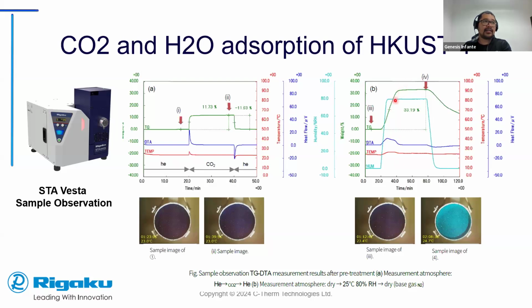And then, as the humidity is being stabilized, it saturates the MOF. But then you can see here, this is really what you want to see, is how does the MOF behave once you want to release that water, right? In a passive way where you don't introduce any energy to the system, you can see that the rate of water loss is a lot slower than the water intake in this case. And then you can see here that at some point when water is actually coordinating within the MOF system, there's a color change from deep purple to this teal color.